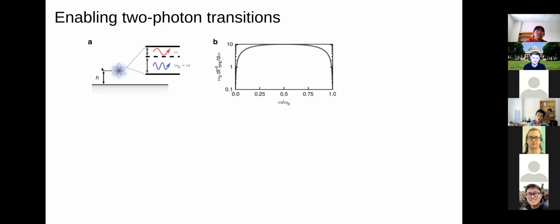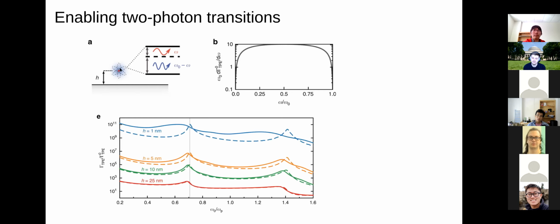However, we can play the same kind of trick that we did with single photon spontaneous emission by taking an atom or a two-level system, quantum dot, whatever it is, and placing it in the vicinity of something that has highly confined surface polaritons, for example. And when you do this, you'll find that depending on how close the atom is to the surface so that it can couple either more or less effectively, the spontaneous emission rate can be enhanced by absurd amounts.